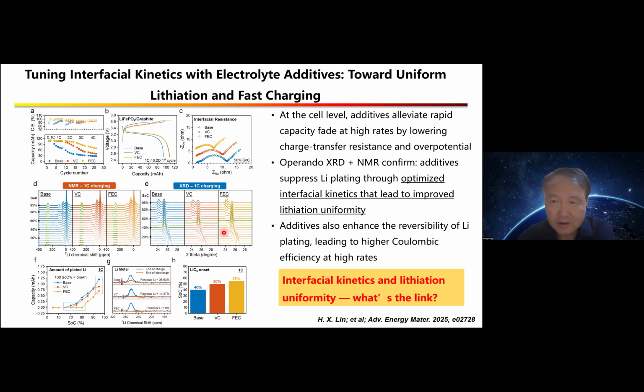But actually, it's not only that additives construct good SEI, but they could also suppress the formation of lithium plating or lithium dendrite, because we found this could cause lower charge transfer resistance and lower overpotential of the lithiation process.